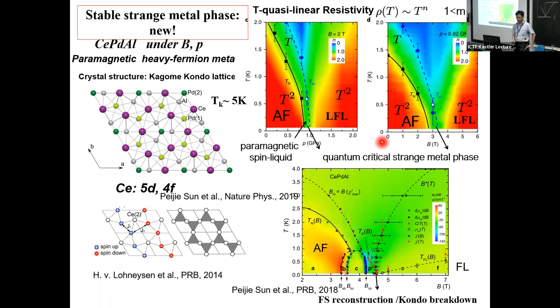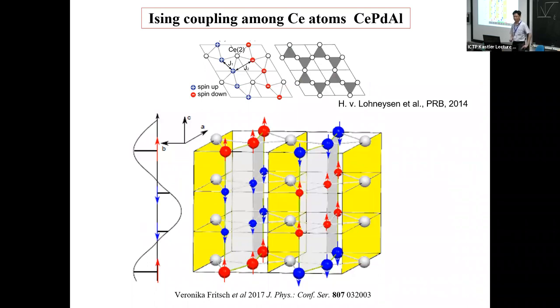The magnetic structure of this material is a little bit complicated. It consists of Ising coupling among cerium atoms, and they are three-dimensional. Along the c-axis, we have antiferromagnetic Ising coupling, so it gives rise to this type of long range order. And in the ab plane, the Kagome plane, it consists of two Ising chains with opposite spins, which are marked by blue chains and red chains. Along the blue and red chains, there are ferromagnetic Ising type couplings, but there is an antiferromagnetic Ising coupling between these two chains. So it's a bit complicated. It's J1 and J2, and also the c-axis antiferromagnetic coupling. The long range order is probably due to this c-axis antiferromagnetic coupling.